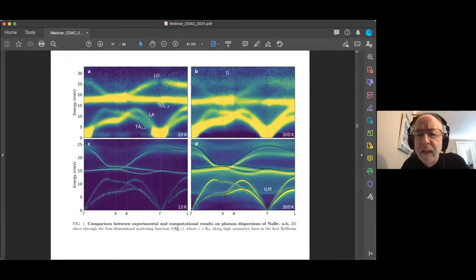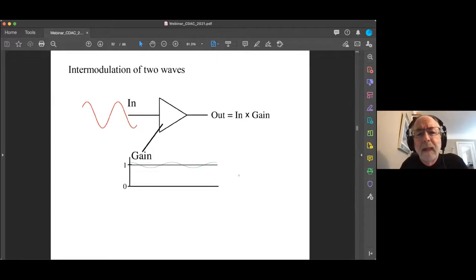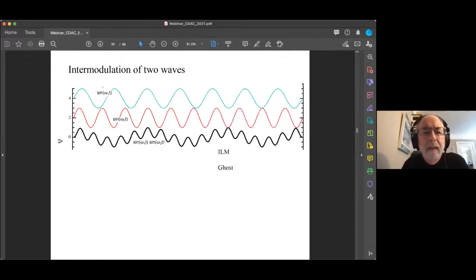But the idea here is that this is an intermodulation effect where we have a medium, sodium bromide, which would have a unity gain. So we put in one phonon and it would have a behavior that comes out directly if the gain of the medium were 1. But if the gain of this medium was being modulated by a very strongly excited phonon of another type, then we could get the product in the output of this red wave times this blue wave, sort of as shown here, where we take the product of these two sine waves and we get this long modulation, and then we get these high frequencies.